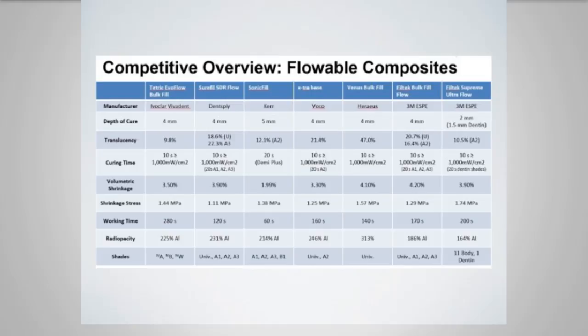And as far as the radiopacity, that's another important factor to me. I do want to be able to see it on a radiograph, obviously. I don't want it to mimic the radiopacities of dentin or enamel. The dentin is about 100%, enamel is about 200%. So if you see the radiopacity over 200%, that means it's going to be brighter on the radiograph than both dentin and enamel, so easily distinguishable. Tetric EvoFlow bulk fill does that as well.